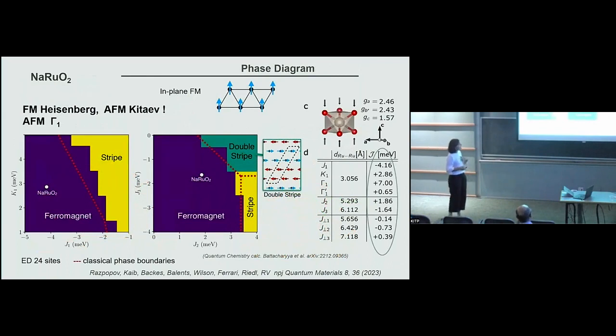But what is interesting is that in this material there is a very strong ferromagnetic interaction, as well as antiferromagnetic Kitaev exchange. And these interactions, in fact, I know I have 0 time. These interactions promote ferromagnetism.